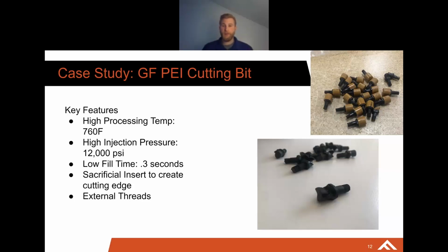They needed 50 pieces, so we ran 60 with a 10-piece buffer. The only sort of wear or anything that we saw was a little bit at the gate, and that was easily trimmable. So all it did was really open up the gate and allow for a little bit lower pressure to be used, but it worked great.